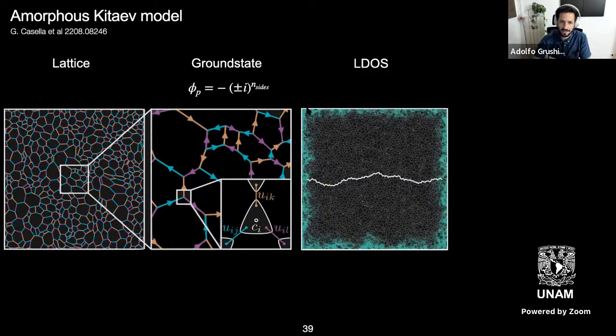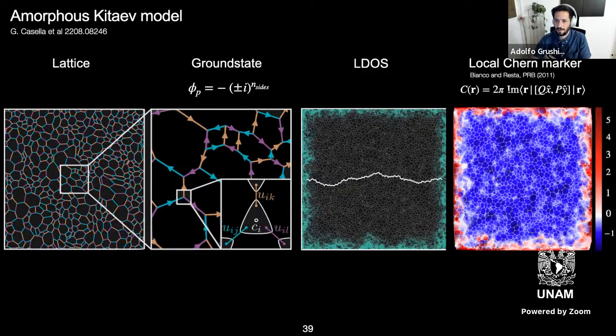And you'll find that in the local density of states, you have an edge state. Forget about this white line. This is just the local density of states, which means that you have a topological state going around. The reason you know it's going around and not just staying there is because you can compute something related to the Hall conductivity, or in this case the thermal Hall conductivity, which is the local Chern marker of these Majorana fermions. You see that it's quantized to -1 in the bulk, and goes up to some very high value at the boundary. This is the typical signature. Even if you've never seen this before, just think of this as some local version of the Hall conductivity, which tells you whether the system is topological or not. And in this case, it is topological.